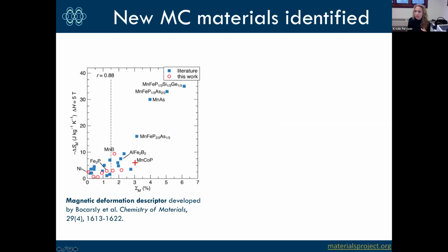So this was a property that excited a collaborator of mine, Ramses Chowdhury at UC Santa Barbara. He plotted the different materials that they were able to see today that had decent Magneto-Caloric response with something he called the Deformation Descriptor, which is basically the calculated volume change of a material between the non-magnetic and the ferromagnetic state, which is a reasonably easy thing for us to calculate. And he was able, using this descriptor, to identify some interesting materials, but we were also interested to see if we could partner with him and scan the whole Materials Project for possible high-performing, large entropy materials, high on this descriptor scale, that hadn't been considered before.